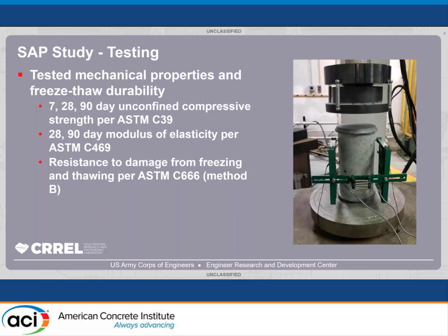The testing that we completed was for compressive strength. We did a 7, 28, and 90-day strength testing. And then for modulus of elasticity, which you can see in this image here, we did testing at 28 and 90 days. And then we did testing for freezing and thawing following ASTM C666. And we followed the B method, where your samples are frozen in the air and then they're thawed in the water. And we followed these all to the specification, except for mixing and curing in that cold environment, in that 23 degrees Fahrenheit room. And we did not moist cure, because you can't moist cure when things are below freezing.